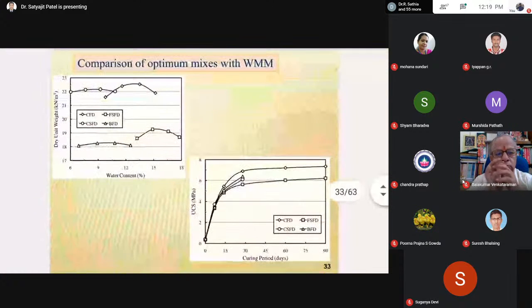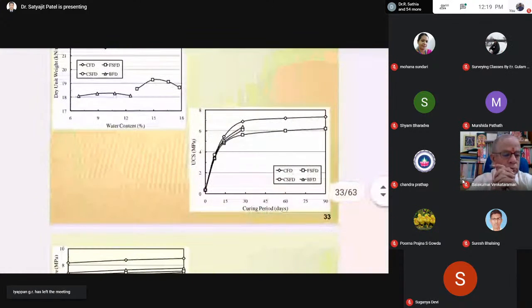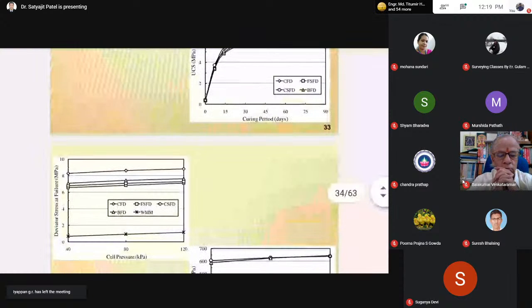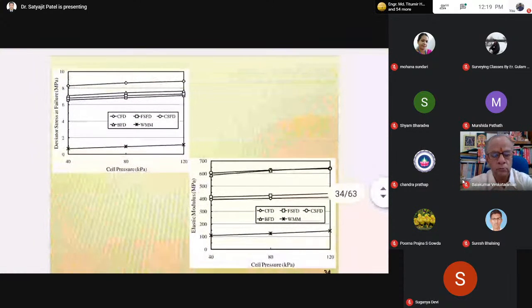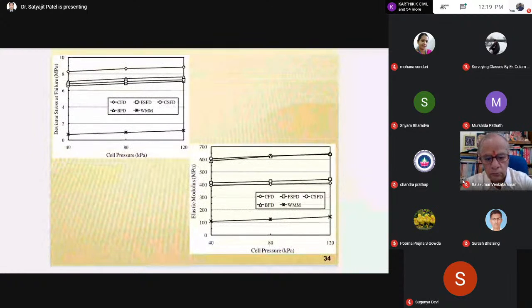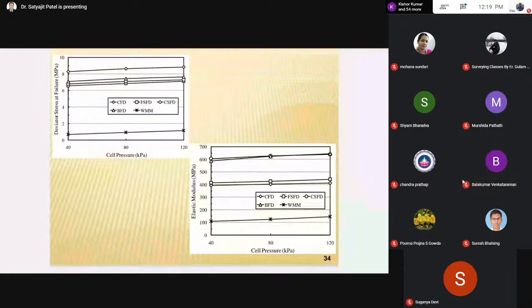So, comparison of these optimum mixes with WMM. If you see here the comparison of all this material, the WMM, that is the bottommost, is for WMM, that is deviator stress to cell pressure, and the cemented waste material has a very high value of deviator stress or failure stress as compared to WMM. So it has a high elastic modulus also. Static test elastic modulus is 460, but you can get only 100 MPa, maximum 150.